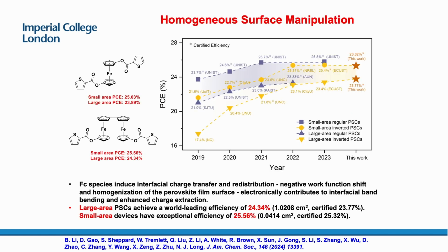So there's quite a lot of material here. As I say, for completeness of time, I don't have too much time to go into depth, but the JACS paper will tell you more about this. But the key thing about this work was what we were able to do. We were able to take what we normally call a small area device and make it a large area device. Now, large area in this field is still only 1 centimeter squared.